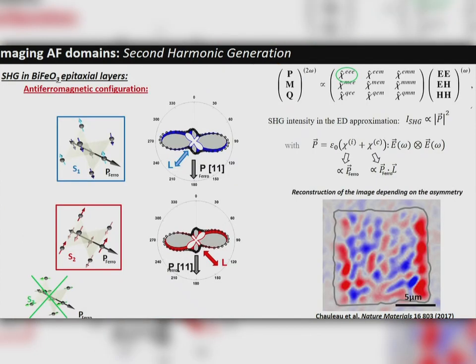And if you do a bit more of analysis, you can note that if you do for a single pixel a full angular dependence, and a bit of symmetry, then you can note that in each pixel, you have two contributions. You have one gray contribution, which is the contribution basically which is only for the ferroelectricity. It's normal, you are in a single ferroelectric domain. And you have a tiny contribution which changes sign from places to places. And by reconstructing this asymmetry, basically, we are able to image the antiferromagnetic domains. So I spare you the detail, but basically we have two contributions. One contribution which is only the ferroelectricity, and one which is basically the ferroelectricity times the antiferromagnetism, and in a single antiferromagnetic domain, then it becomes the antiferromagnetic vectors. So here it is what we can do.